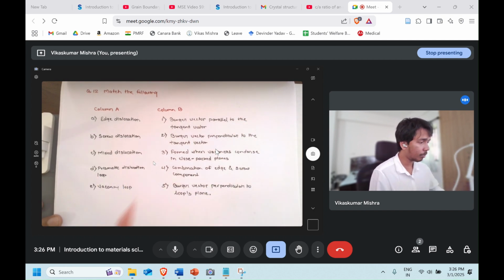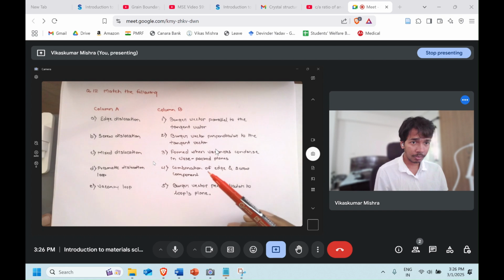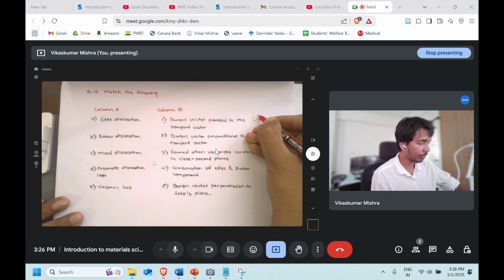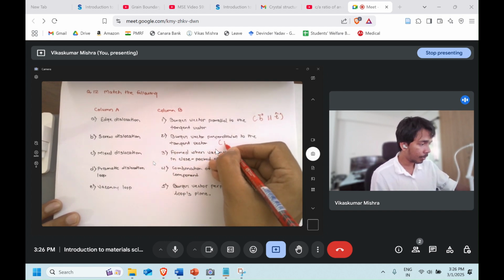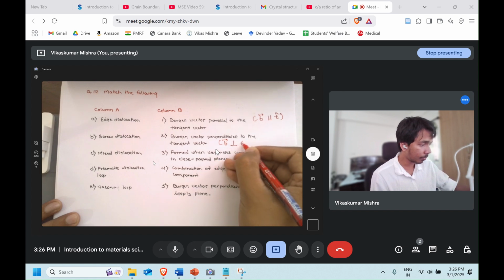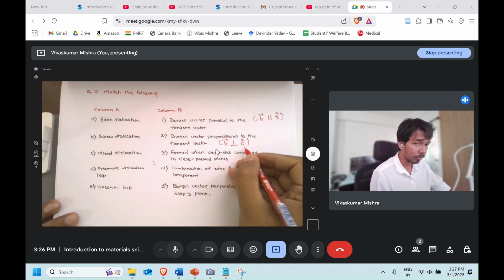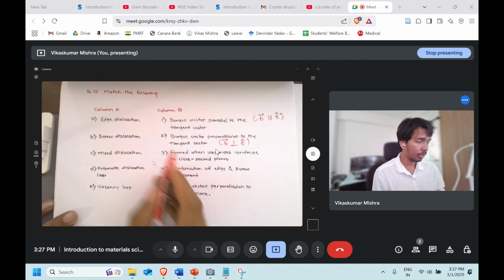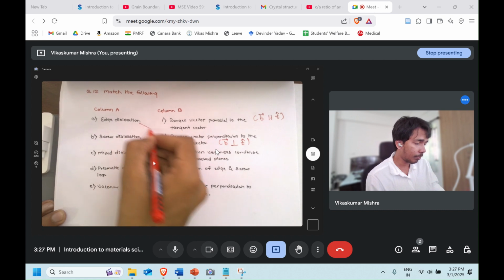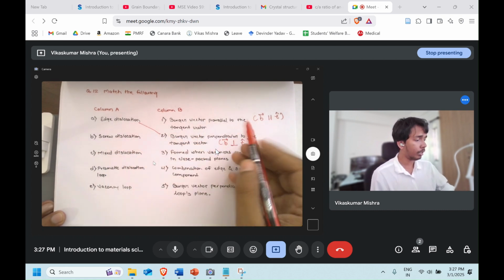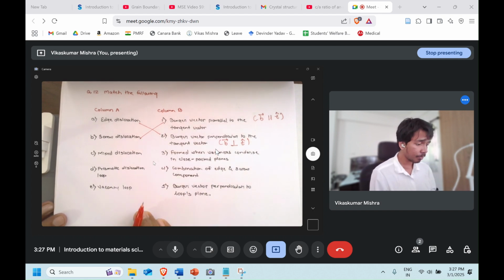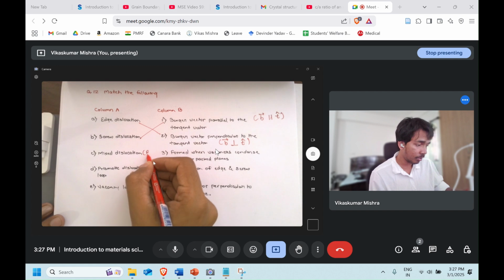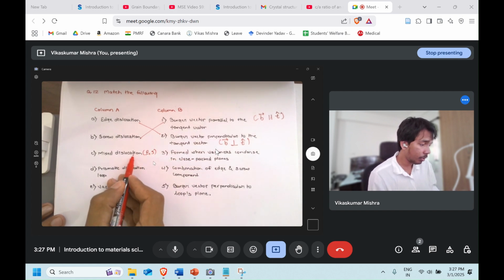So let's talk about the screw dislocation. The Burgers vector parallel to the tangent vector. So here they are telling that the Burgers vector is parallel to the tangent vector, that is the dislocation line. Second case, Burgers vector is perpendicular to the tangent vector, that is, perpendicular to the dislocation line. We know in the edge dislocation, this is the case where the Burgers vector and the tangent vector are perpendicular to each other, while in the screw dislocation, they are parallel to each other. Regarding the mixed dislocation, a combination of the edge and the screw component, it will have both edge and screw components. So it will match with option 4.